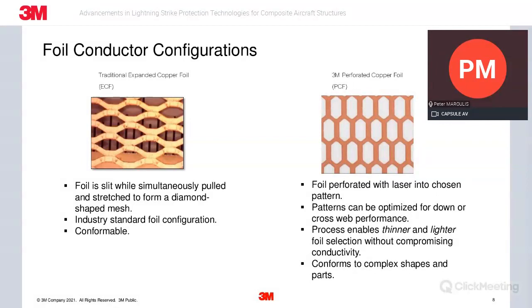So what 3M has been working on as a design is a perforated solution that doesn't have the excess copper in those node points. If you look at the cross section at any given point in the perforated copper foil in the image on the right, it is constant throughout, and this is one of the ways we've been able to take a decent amount of weight out of our solution.